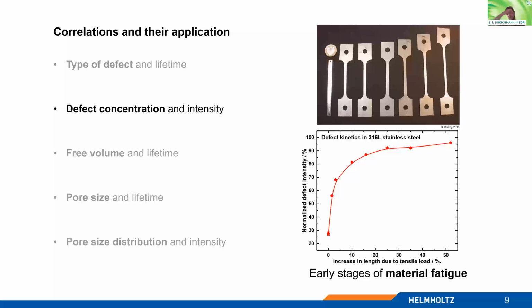What else could be said? As I said, the intensity can also be used as a monitor for defect concentration. Here, for example, we measured the defect kinetics in stainless steel and measured the positron lifetime, or in this term, the increase of the defect intensity for an increase in the tensile load. So this is a standard stress strain test, and yes, you see in the first 5% of changing the length of this metal, the defect intensity increases significantly.